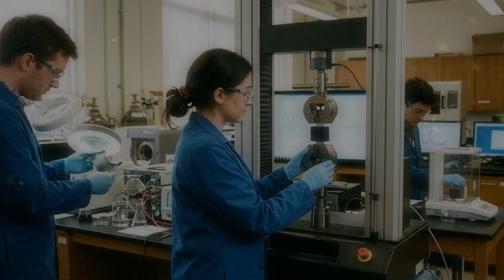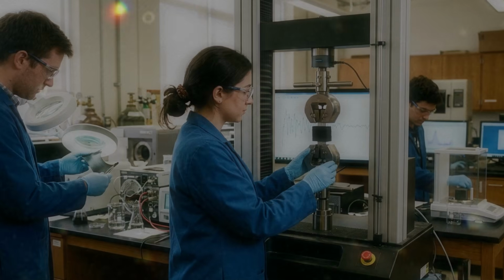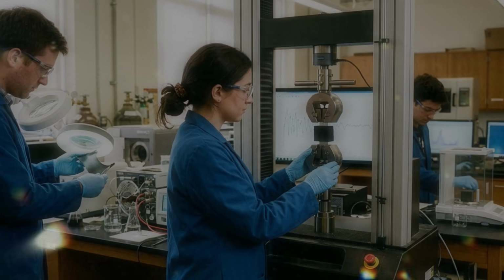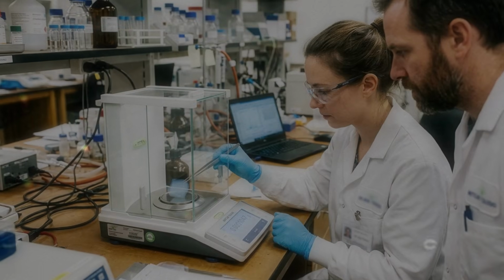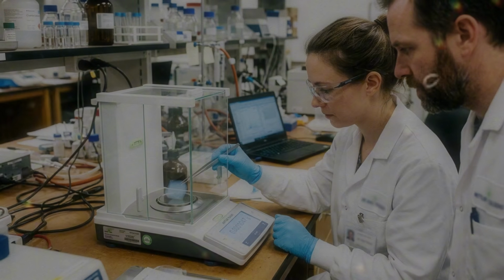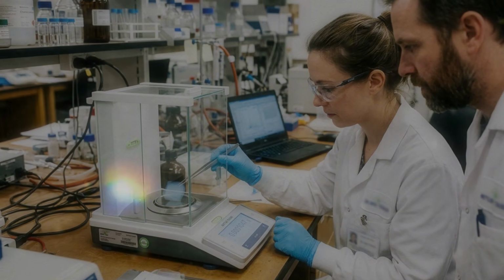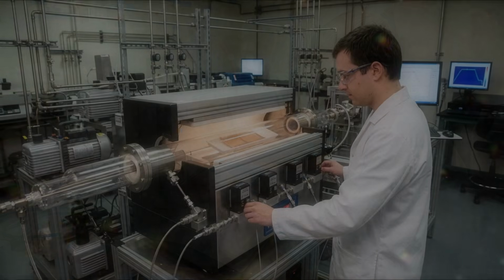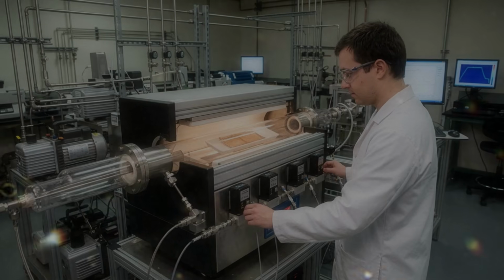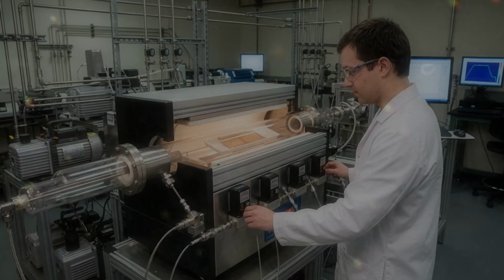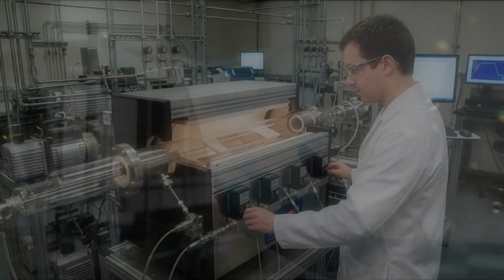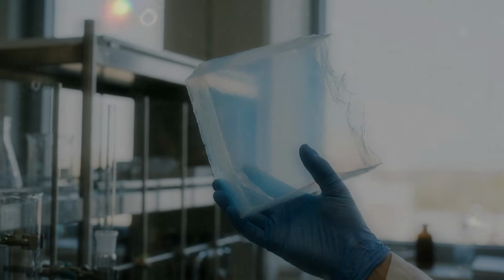Supercritical drying is not the only option. Freeze drying can also preserve porous structures. In this method, the liquid inside the gel is frozen and then removed by allowing the solidified solvent to pass directly into a gas under reduced pressure. This avoids the usual liquid surface during drying, but freezing creates its own difficulties.